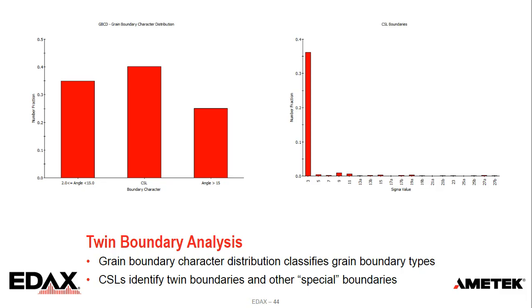The distribution on the right characterizes CSL boundaries by what are termed sigma values. CSLs are a boundary model, showing the frequency of shared lattice sites between two different lattices for adjacent grains. And so we get an idea that in this case there's a high fraction of sigma 3 boundaries. Sigma 3 corresponds to those 111 60-degree rotations. But we can also see there's a small little peak at 9, which would be a twin of a twin boundary. And so we get a lot of information about grain boundary character with EBSD.